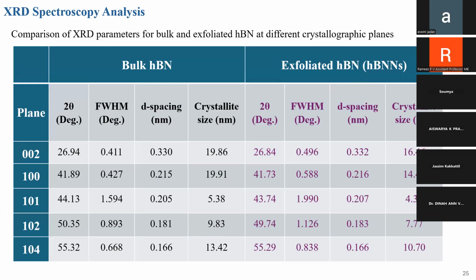Crystallite size you can find out by the Scherrer equation, D = Kλ/(β cos θ). And you can get the d-spacing with the help of Bragg's equation, nλ = 2d sin θ. Likewise, you need to find each value and compare these two materials, specifically the bulk and exfoliated HBN. You need to give an inference on how you can say that it is exfoliated while keeping the integrity of the crystallinity and atomic structure.